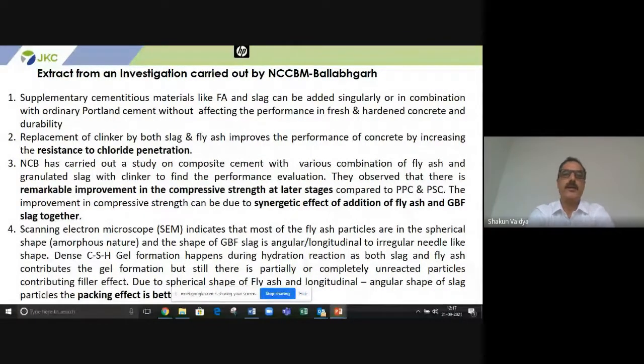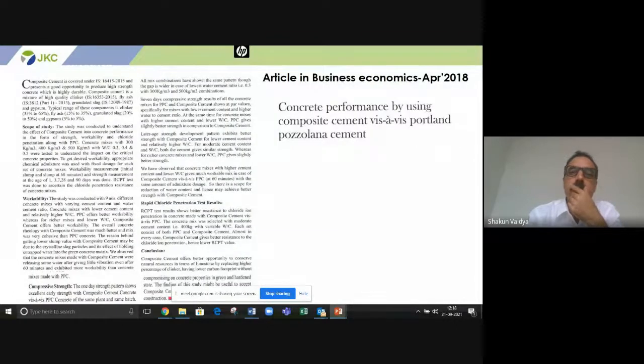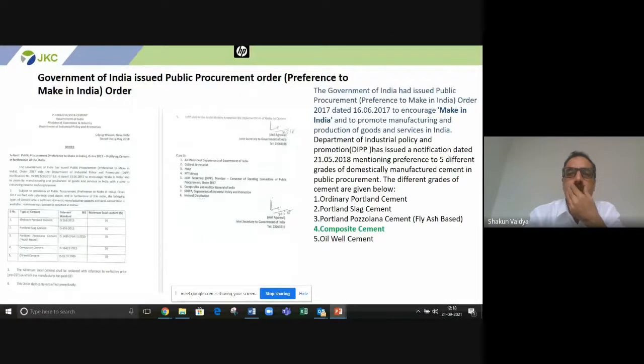So NCB carried out a detailed investigation on resistance to chloride penetration, as was shown earlier, and there was a remarkable improvement in the compressive strength of composite cement concretes at a later stage. The synergetic effect of the addition of fly ash and GGBS together gave this benefit of better strength at a later stage. And the synergistic benefit of both GGBS and the silica particles of fly ash and slag gives a better packing density as well. A lot of publications have published studies about composite cement vis-a-vis other variants, and obviously this is an established fact that it is better than OPC.